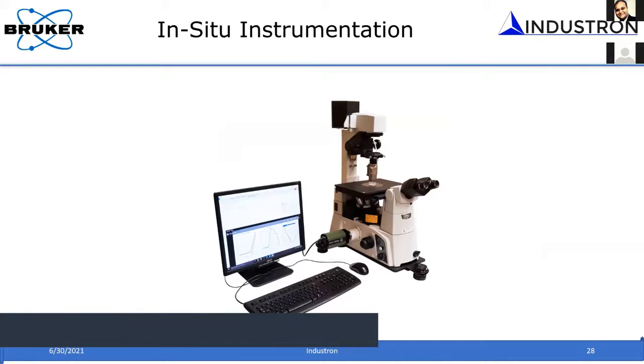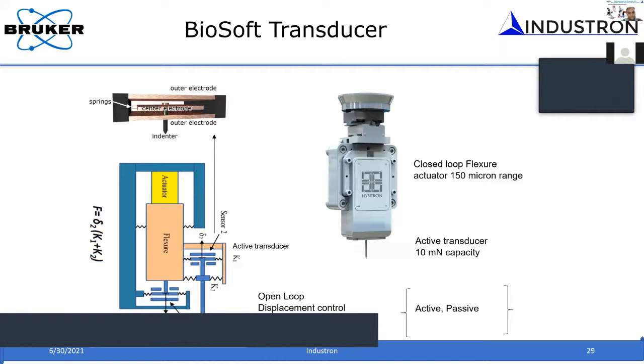We call it the BioSoft bioindenter, which is basically a transducer capable of applying very small forces with high force sensitivity, but also has a very large displacement range. It has the same elements, for example the capacitance sensor normally used in our typical high-strength transducer, and you still have that, but it is used in combination with a flexure actuator and an additional sensor, so you can go for a very large displacement range, about 150 micron, but at the same time keep the same force sensitivity that we have with the normal transducer that we use in our 950.